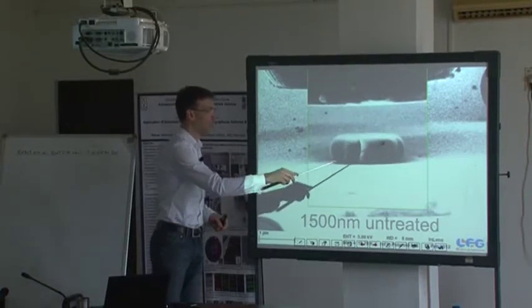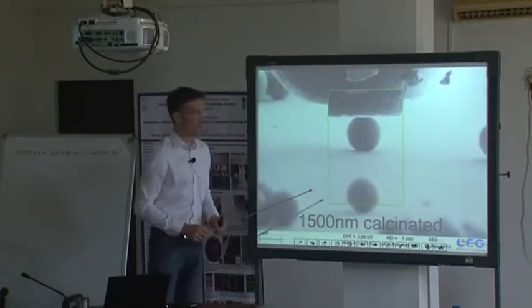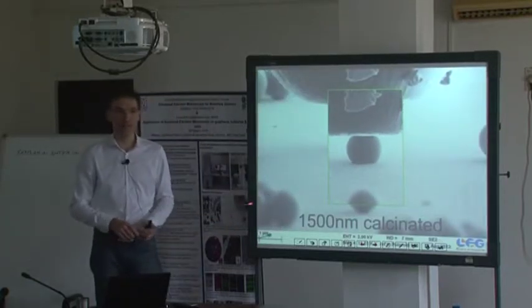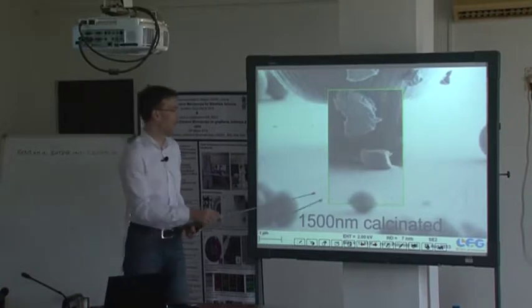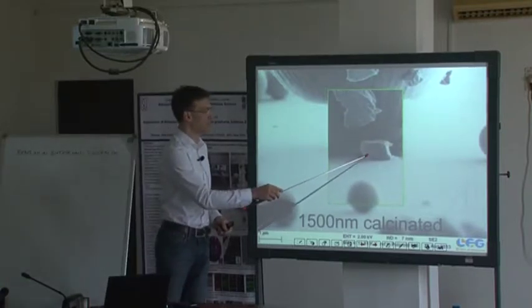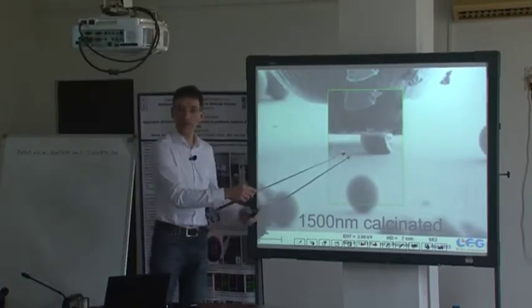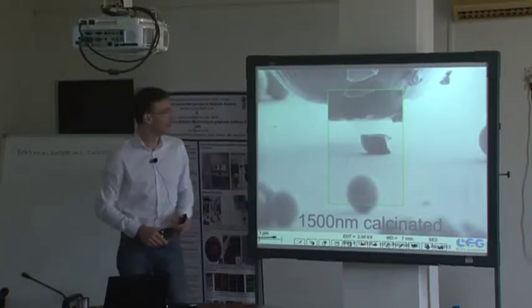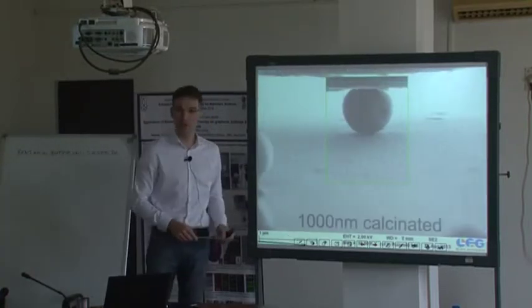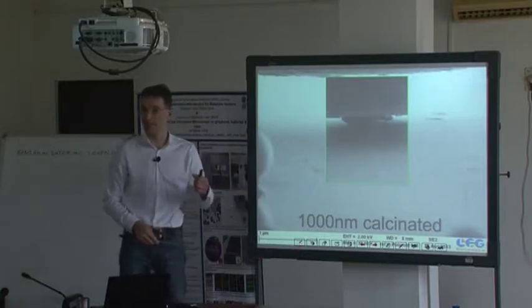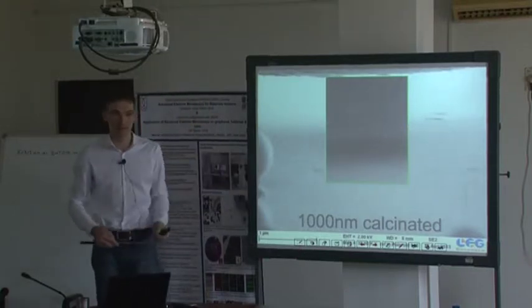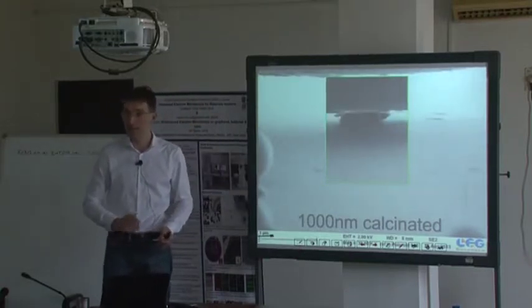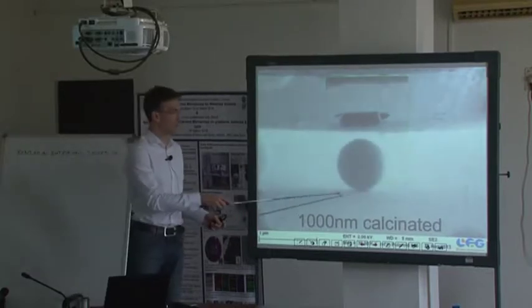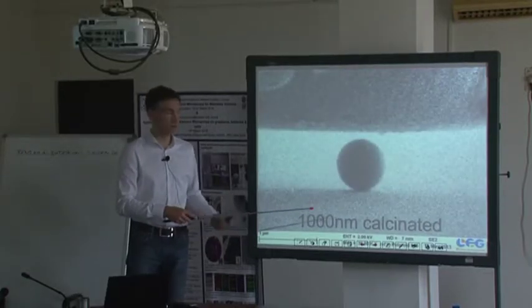And depending on the density of these particles, they are synthesized by a wet chemical route, and they exhibit a certain porosity. So this is quite brittle, the other one was a different particle. And you can test not only a single particle, by this you can do statistics. You can indent, let's say, 10,000 particles, that just takes you 1 day, and you can come up even with the load displacement curve by that.